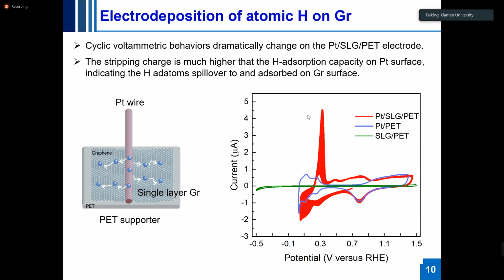We can see in the right figure the blue line. This green line was performed in 0.5 molar sulfuric acid with the PET-supported single-layer graphene electrode. We can see that there's no reaction in the whole potential region. That means the protons cannot be reduced electrochemically directly on graphene. The other line is the PET-supported platinum wire. We can see a very clear hydrogen region at a lower potential. This is the protons being reduced to hydrogen atoms on platinum.